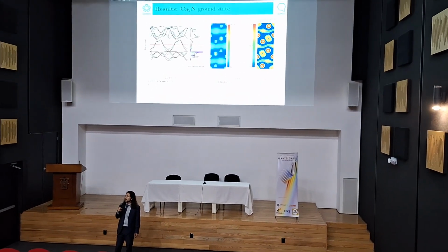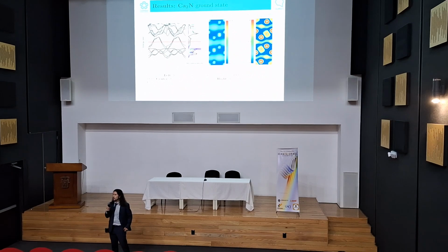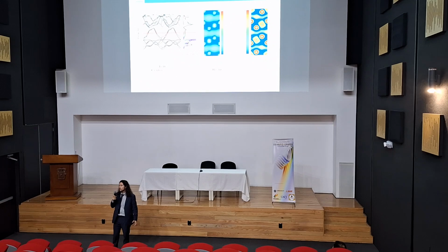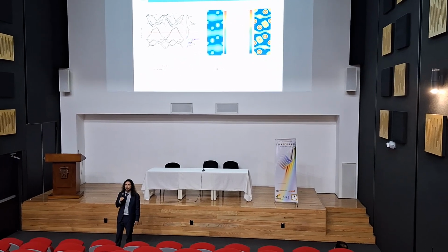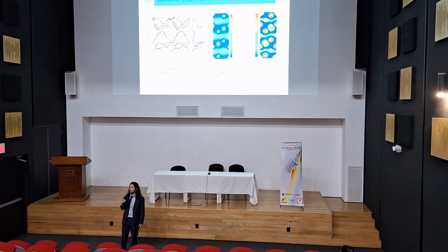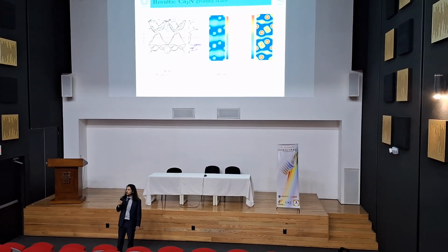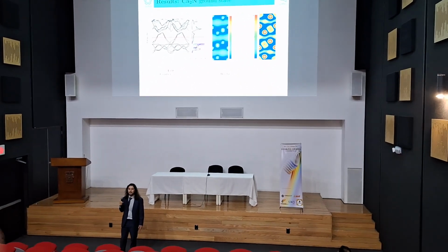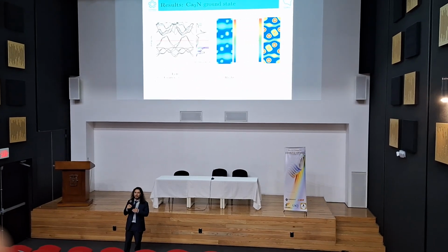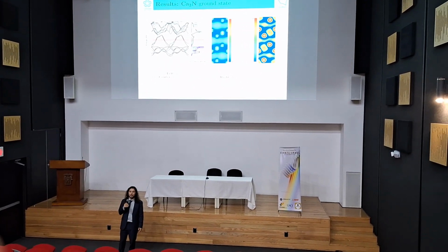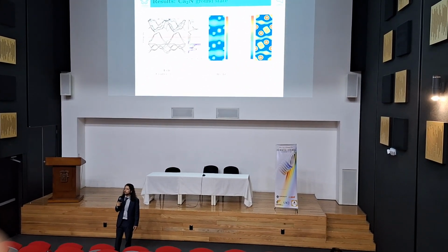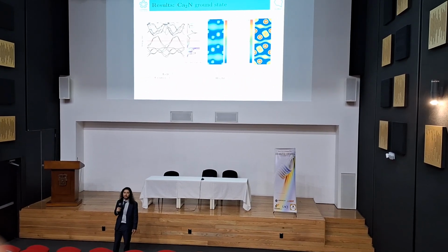We can contrast this with the local density of states, which means the number of states per volume and per unit energy. This plot shows the local density of states at the Fermi level, and as you can see, in between the layers we have a greater contribution to the density of states, which is due to these three bands.